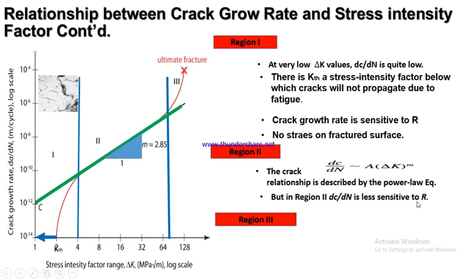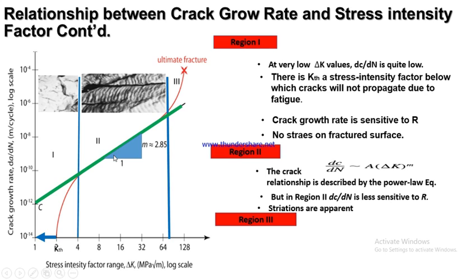Another thing we're supposed to understand in this region is that we have less sensitivity to the stress ratio. The stress ratio is not prominent in this particular region of the crack growth rate versus stress intensity factor profile. This is where we have what we call striation. You can easily see striations begin to occur in the material here. So when striations occur, you know that the material has passed the threshold stress intensity factor and it's now in region 2 of the profile.